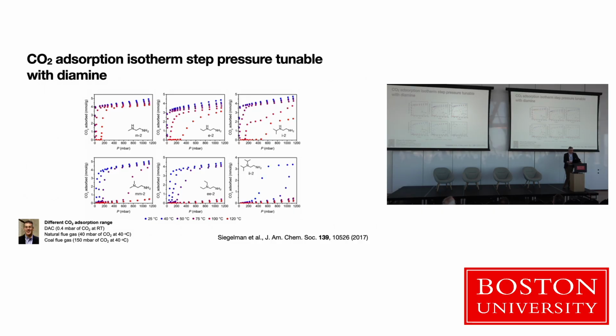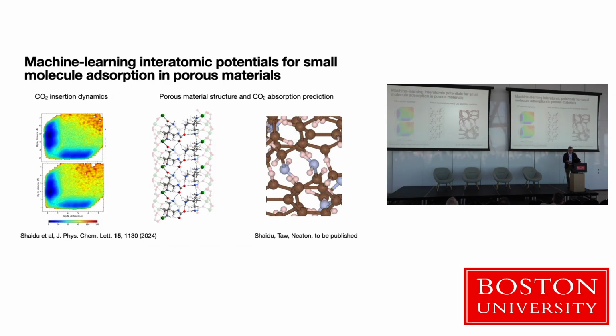and depending on what that is, one can change the threshold, and one can actually even achieve regimes where you're seeing the adsorption under atmospheric conditions, 400 parts per million, or natural gas flue gas, or coal flue gas. These materials aren't commercialized, there are scaling and other issues, but they actually have tunability in the range of interest for carbon capture applications.